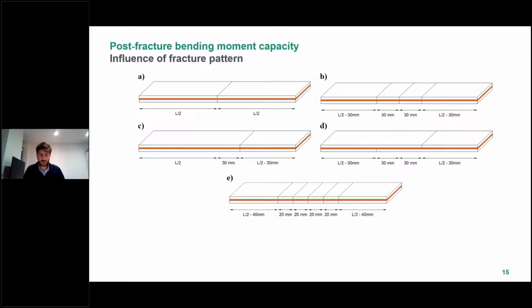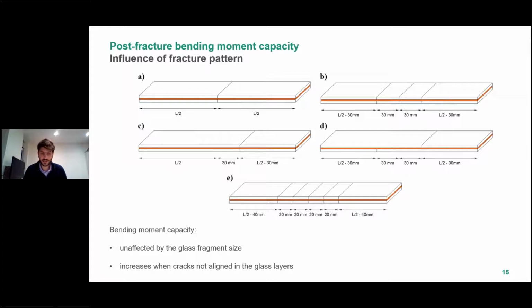To assess if the idealized pre-fracture pattern considered is representative of the random fracture pattern forming under blast loading, the low temperature bending tests were also repeated on specimens with different pre-fractured patterns. The key conclusions of this investigation were that the bending moment capacity is unaffected by the glass fragment size, and it also increases when the cracks are not aligned in the glass layers. Therefore, we can conclude that this idealized pattern will result in a lower bound estimate of the post-fracture bending moment capacity for a specimen with a real random fracture pattern forming under blast loading.